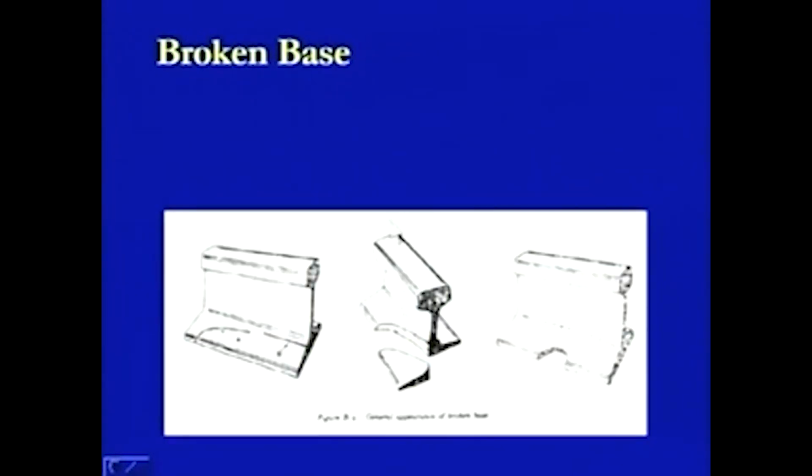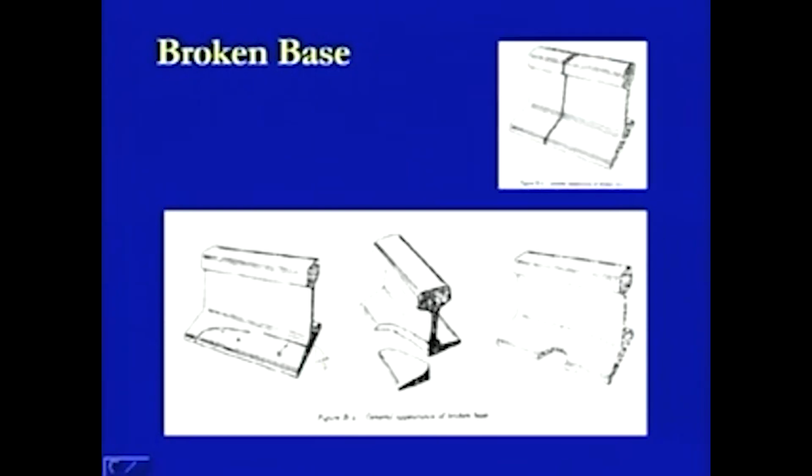Then these are some damaged conditions where we can see that the whole of the piece has come out in this case. On this side, the section is breaking down from the side, this is at the end it is breaking down, and this is the starting of the breaking of the section with respect to the point of connectivity of this web section with this footed condition, and this is the curve of the fillet which will be there at this point. So, this type of failure can also be there, and that is what is a broken base failure.